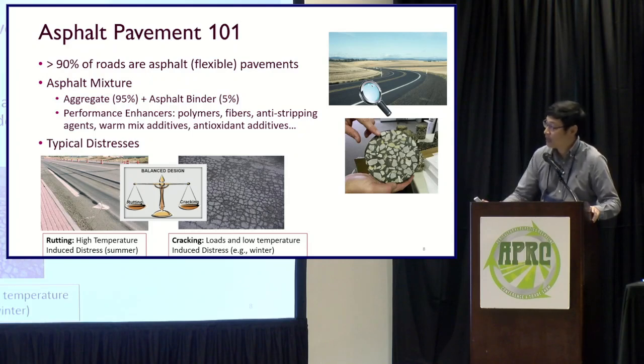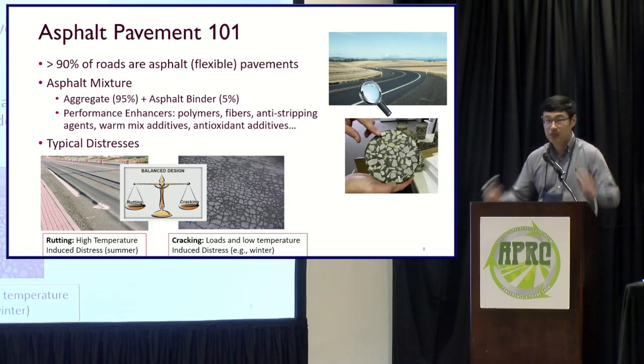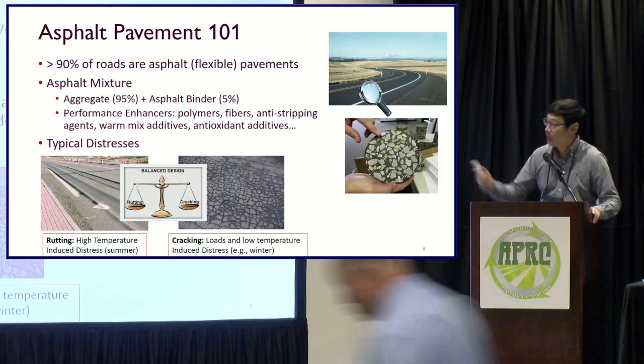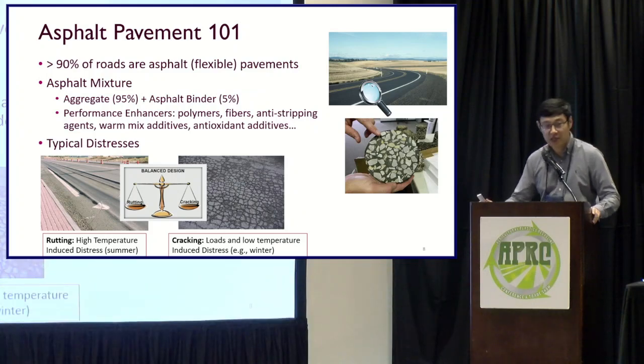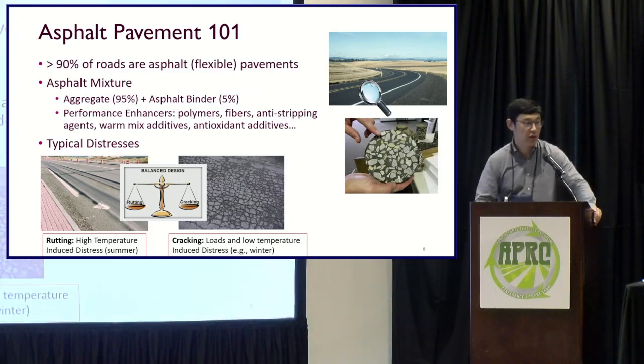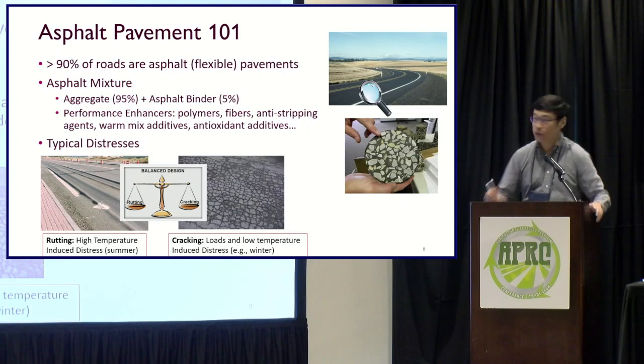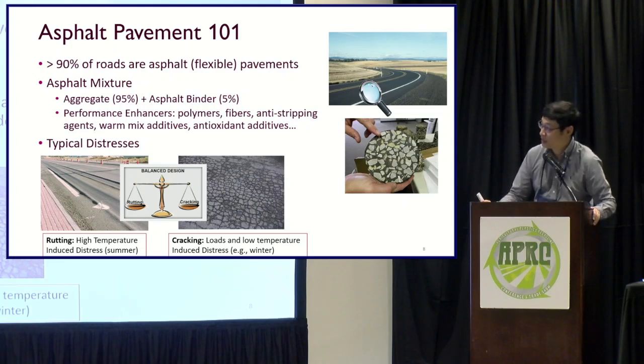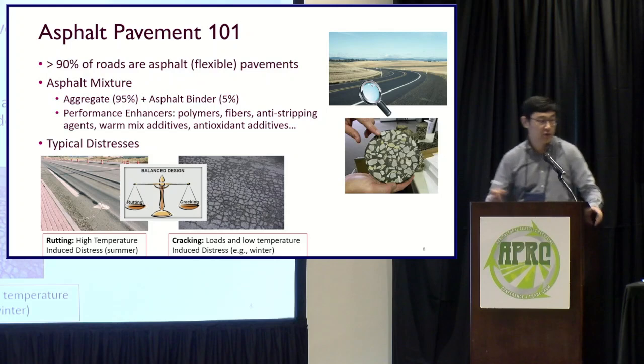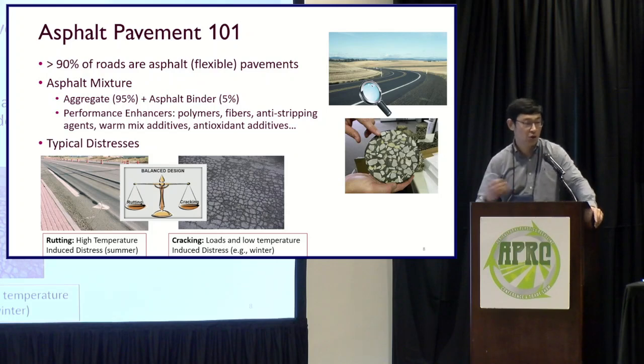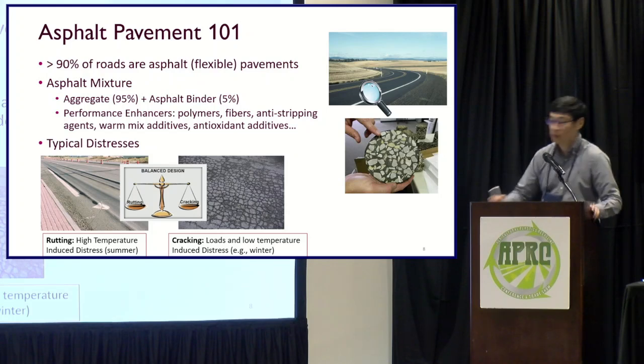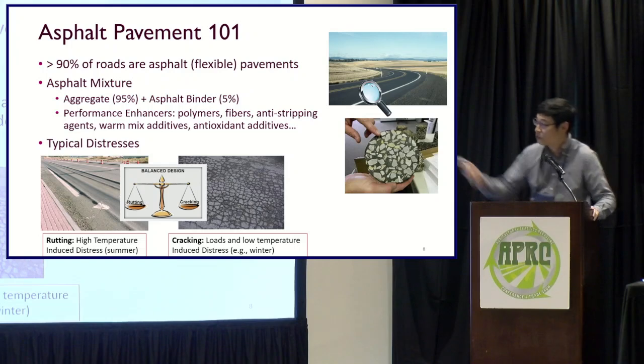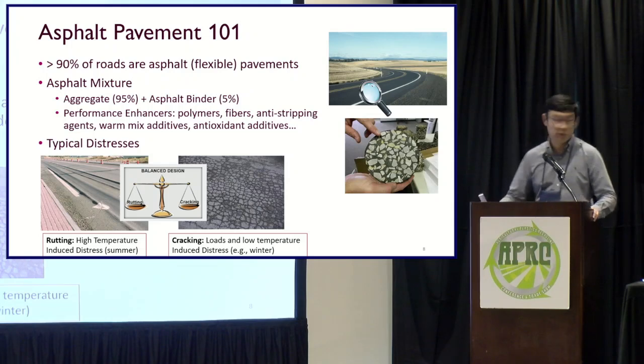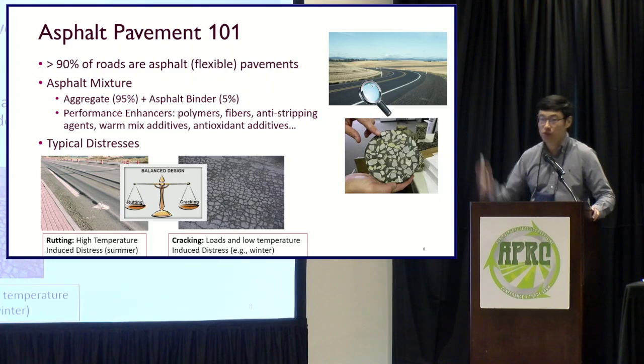So we use the anti-stripping agents that can reduce the moisture damage, and we use the warm mix additive to reduce the production temperature and reduce the fuel use. That's a warm mix additive, and also we use the antioxidant additive in asphalt to retard the aging of the asphalt. So that can extend the service life of the asphalt pavement. So we use a lot of things in asphalt, not only the aggregate and the asphalt binder. So we use the additives.